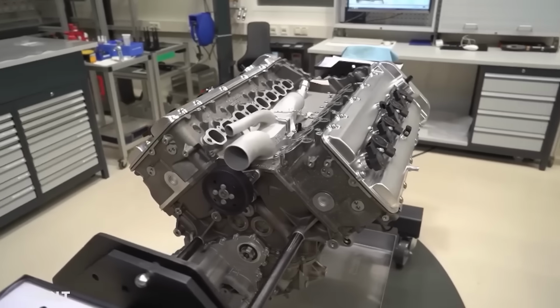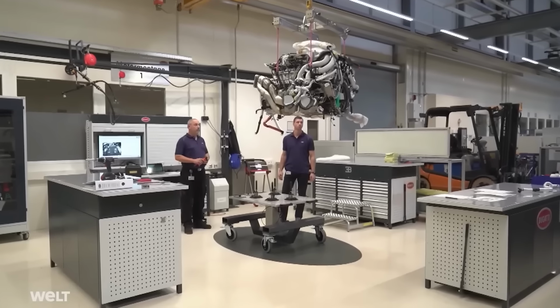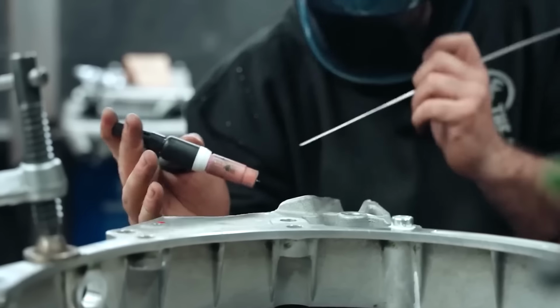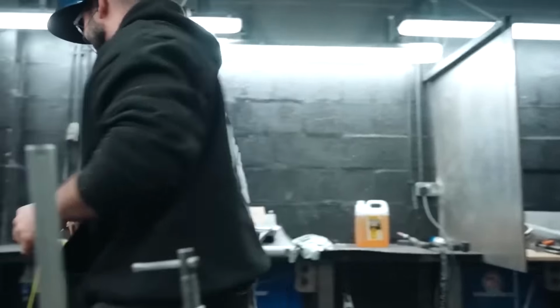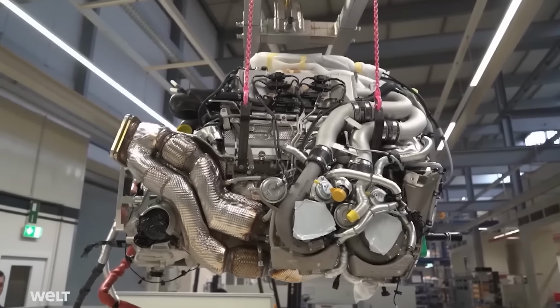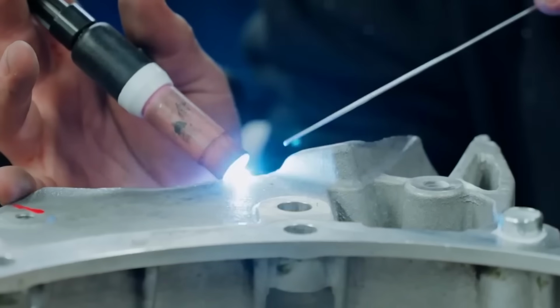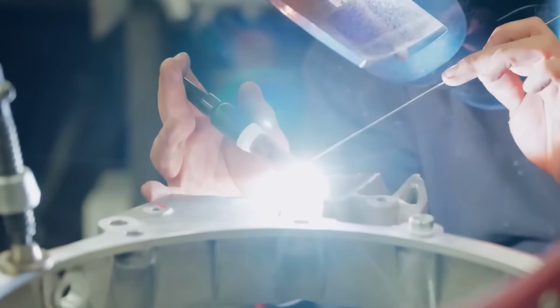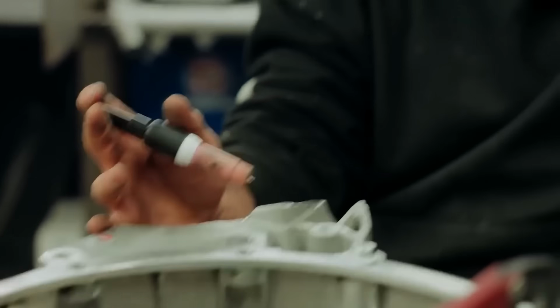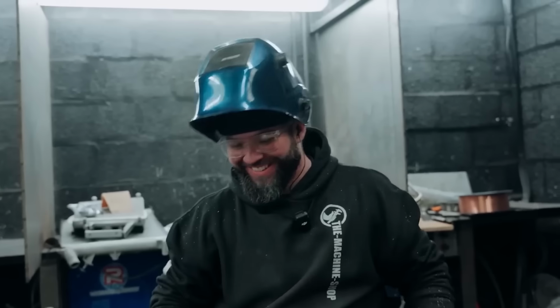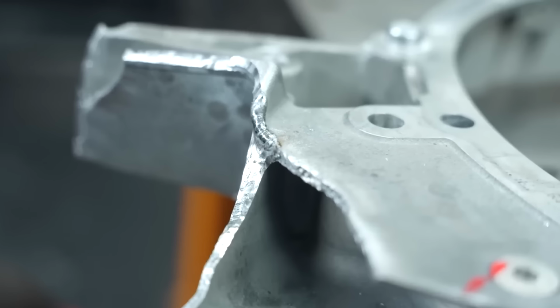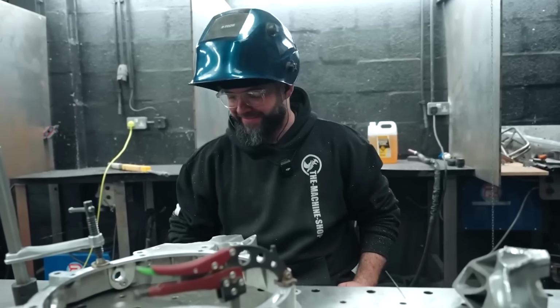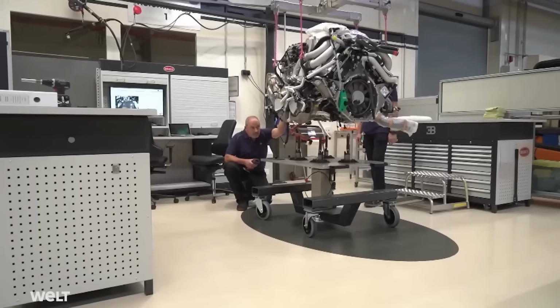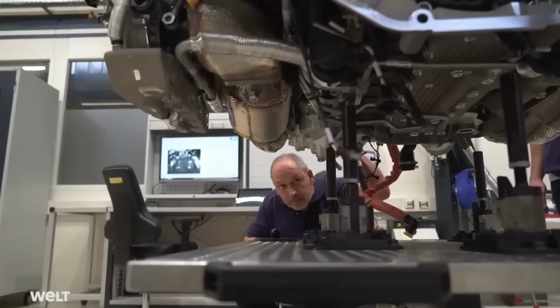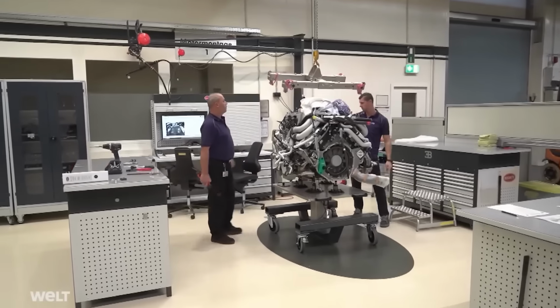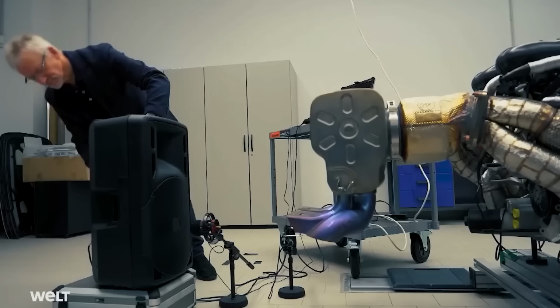Now comes the question that has been hanging over this entire project from the beginning. Can this alloy actually be welded? The mount is cast from A357 aluminum, a high-strength alloy containing silicon and magnesium, commonly used in aerospace and high-performance automotive applications. In theory, it's weldable. In theory. But cast aluminum is notoriously tricky. Porosity, contamination trapped inside the casting, unexpected alloy behavior under heat, these are the things that can turn a promising repair into a cracked, ruined mess. No amount of planning fully answers the question. Only a real test weld will.